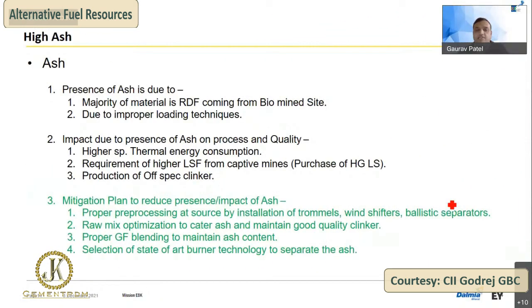Ash is also similar: mostly from biomining sites, and dumping and loading techniques increase the ash percentages. This will also have an impact on energy consumption. The major impact is that we have to purchase high grade limestone if a particular quality of limestone is not available with us. And the ultimate result, if we don't maintain the quality, is the production of off-spec clinker, which is not our aim. So the mitigation plan is proper pre-processing at source by installing trommels, wind shifters, and ballistic separators. The main thing is raw mix optimization to cater to ash and maintain good quality of clinker.